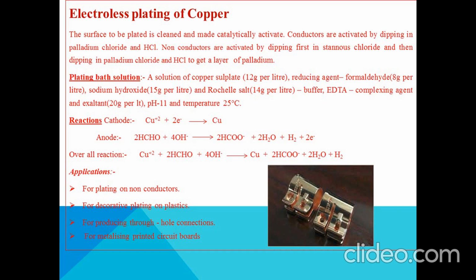The reactions that take place during electroless plating of copper are like this. The reducing agent formaldehyde reacts with the hydroxyl ions and undergoes oxidation, liberating electrons. This reaction takes place on the surface of the substrate and is the anodic reaction. The electrons released by the reducing agent are taken up by the metal ions and they undergo reduction to form metal atoms. This reaction also takes place on the surface of the substrate and this reaction is called the cathodic reaction. The overall reaction can be written like this.